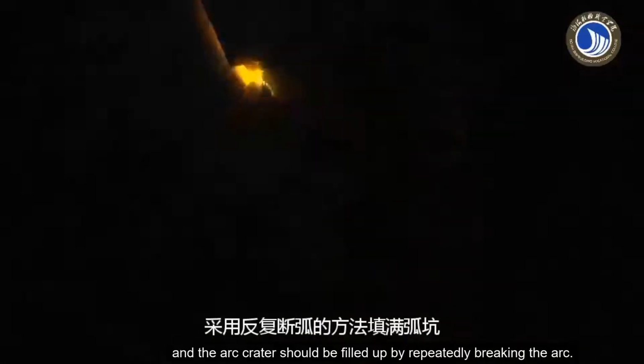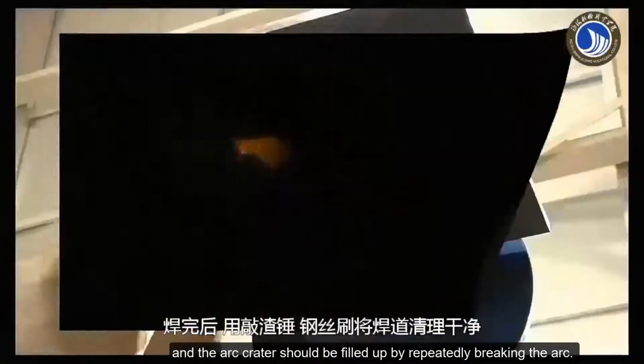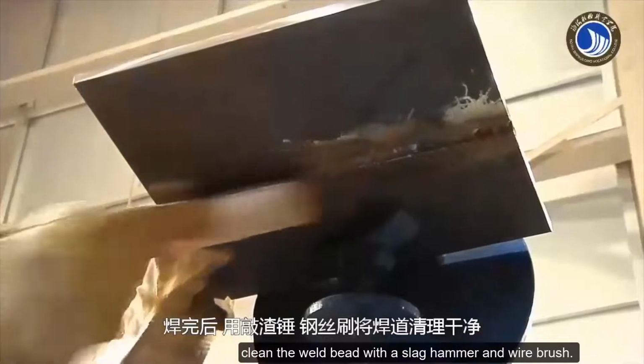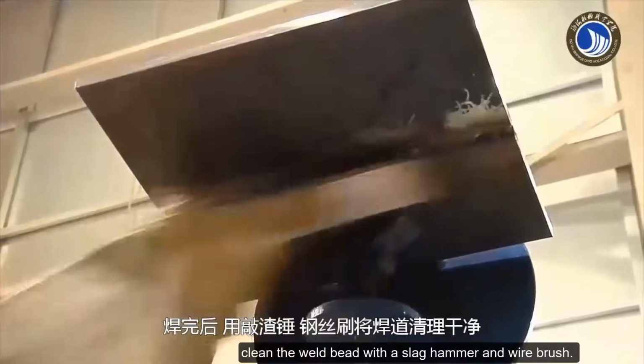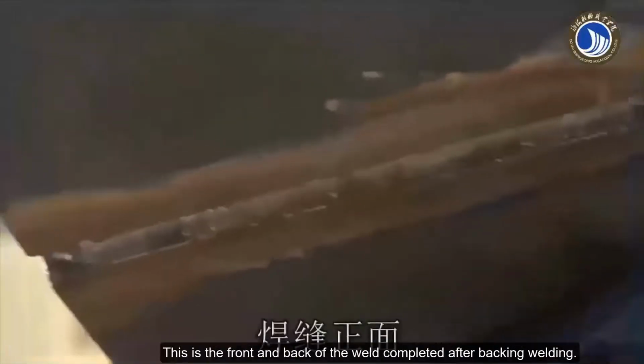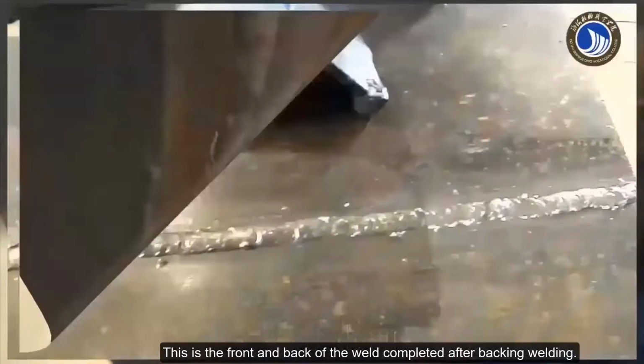When welding reaches the tail position, the arc should be lowered, and the arc crater should be filled up by repeatedly breaking the arc. After welding, clean the weld bead with a slag hammer and wire brush. This is the front and back of the weld completed after backing welding.